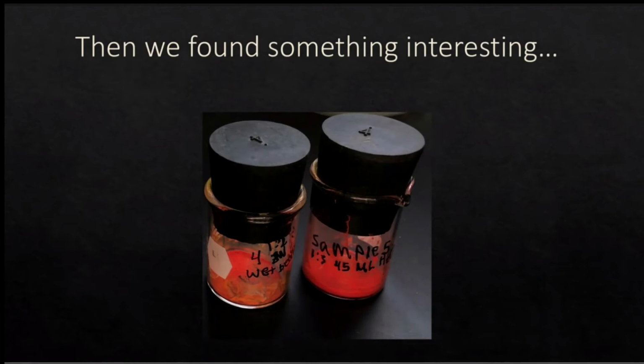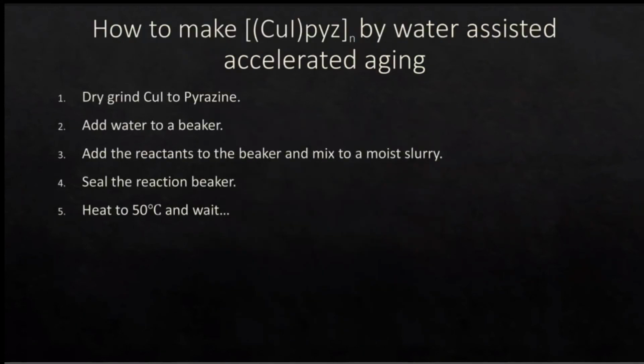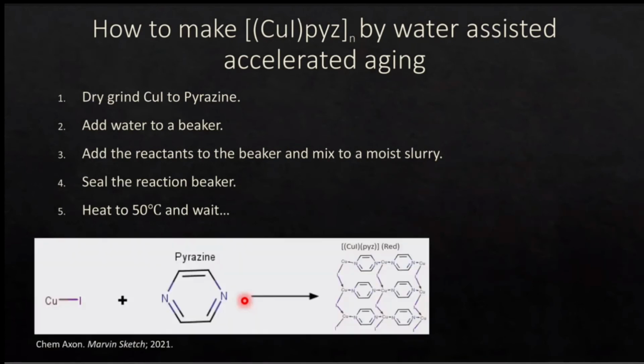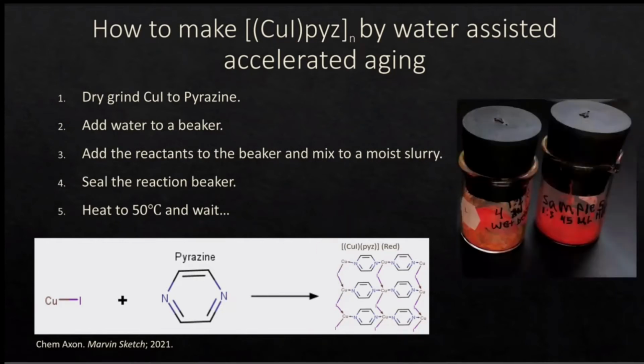We were able to do this through a much more earth-friendly and a much faster process. And after really working through the ideal setup for this reaction, we came up with this procedure. So the idea is to just dry grind the ingredients, so dry grind copper iodide and pyrazine, and you add water to a beaker, but not to the pestle and mortar where you ground the materials. And then you add those reactants to the beaker and you mix it up into a moist slurry. We seal that beaker up so that way the water can't escape. We heat it up to 50 degrees, and then over the course of about 30 to 40 minutes, the copper iodide and pyrazine will go to this red structure, this red polymorph. Now you see the structure up here. And that's how we derive these bright, brilliant red results.